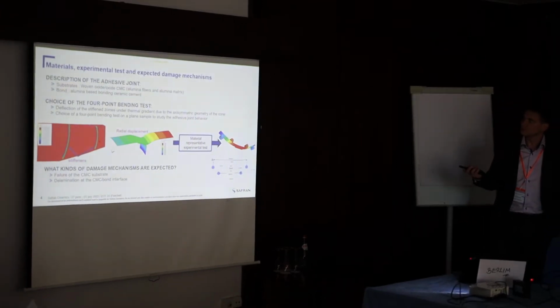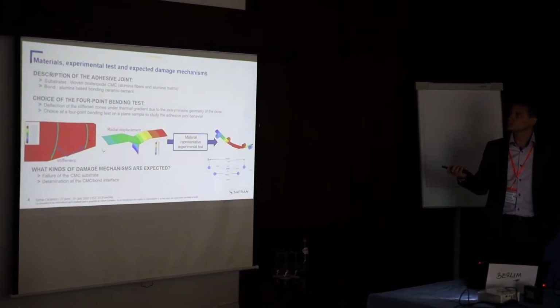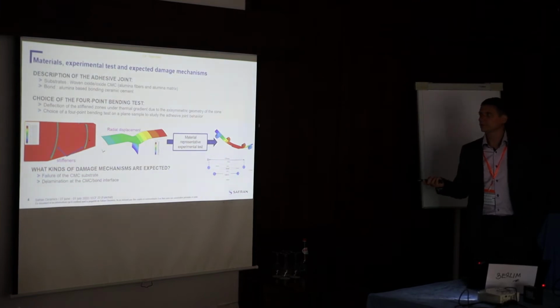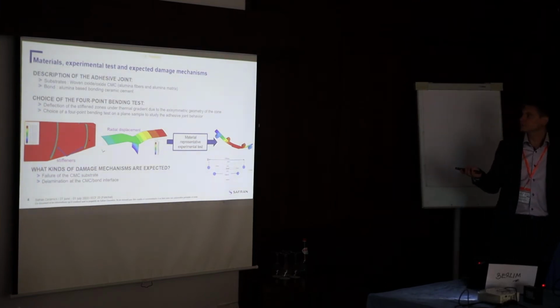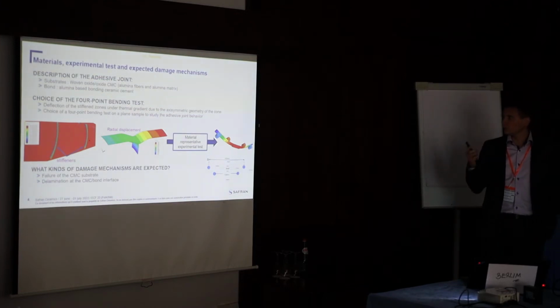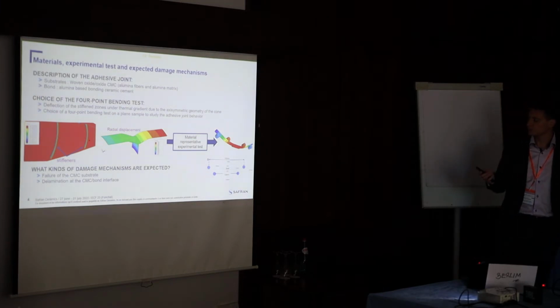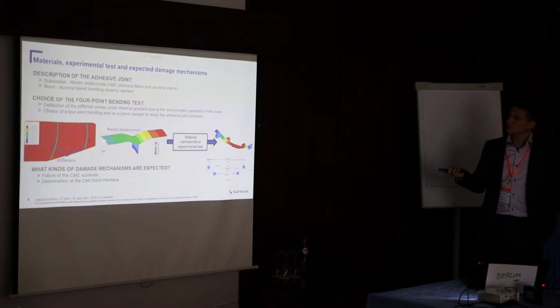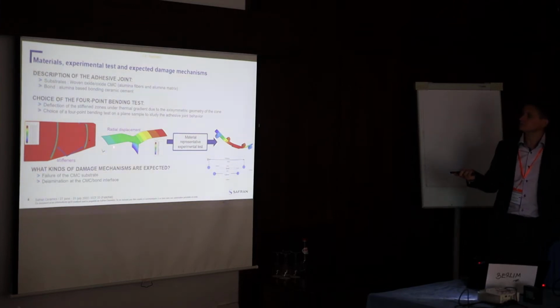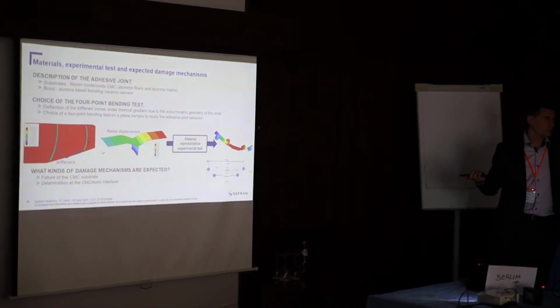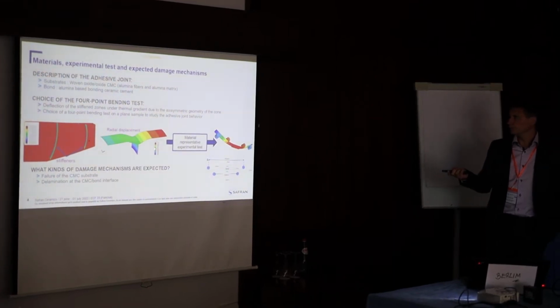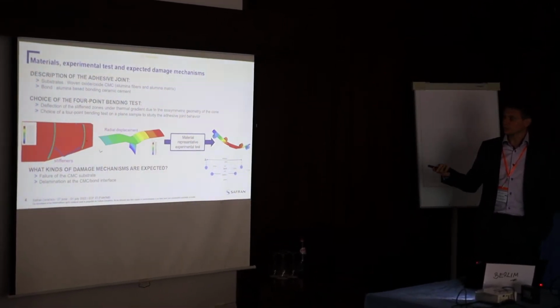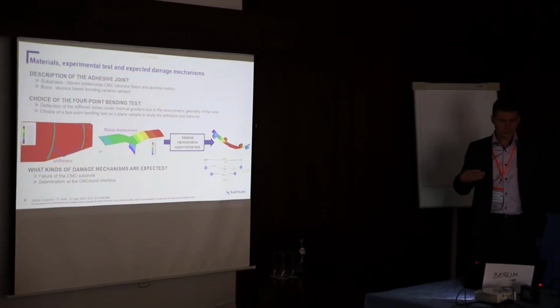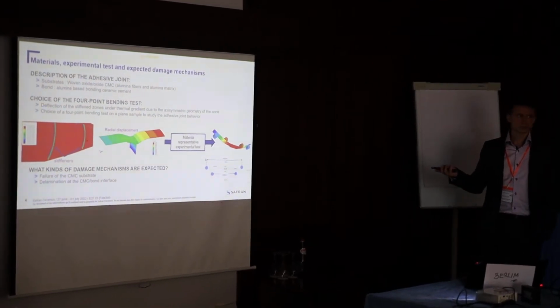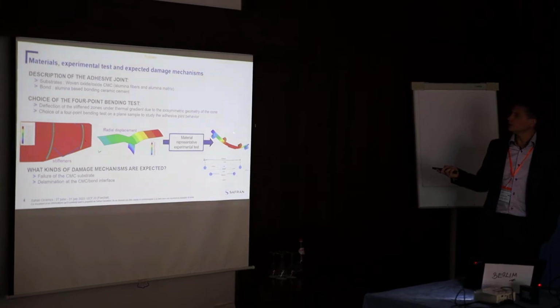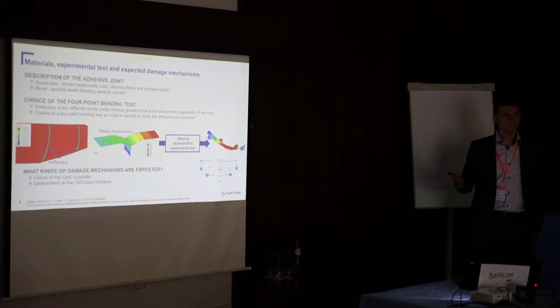In this presentation, we focus on the adhesive joint. For the substrates we use woven oxide-oxide CMC materials with alumina fibers and an alumina matrix, and for the bond, an alumina-based bonding ceramic cement. Why have we chosen a 4-point bending test? Because when we look at the deflection of the structure and the thermal gradients on the stiffeners, it is due to the axisymmetric geometry of the cone. When we would like to understand the damage mechanisms of the material, and justify the strength of the structure, we can take a 4-point bending test as a representative experimental test.